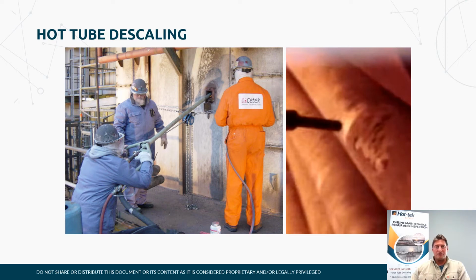But what we're seeing usually with the hot tube descaling is we're trying to reduce either the scale is acting as an insulator, so we're losing too much capacity, or we are seeing that the scale is starting to tree bark, starting to delaminate or fall off of the process tube. And because of that, the process itself isn't cooling the scale anymore. So we're getting very, very high temperatures, sometimes 200, 250 degrees above what the actual tube is, because there's no process cooling that area. It's just like a flake that's heating both sides of the scale itself. All those loosely adhered scale particles can be removed with the hot tube descaling process.